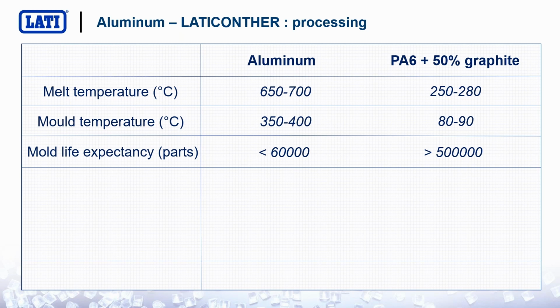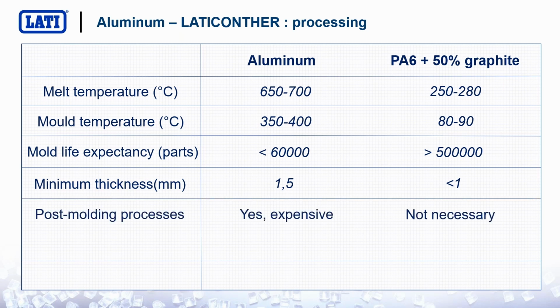If you are very good at die casting, you can rely on maybe 30 to 60,000 shots. With plastics, you can rely on more than 500,000 shots. But I am aware of molds lasting 2 million, 1 million shots. The minimum wall thickness that you can fill with aluminum is more or less 1.5, but with these thermally conductive plastics based on graphite, you can go well below 1 millimeter. The post-molding processes can be very expensive for aluminum, and they are not necessary for graphite. You pull out from the mold the finished part. There is no more sandblasting, despruing, there is no more painting, there is no more washing, there is nothing.